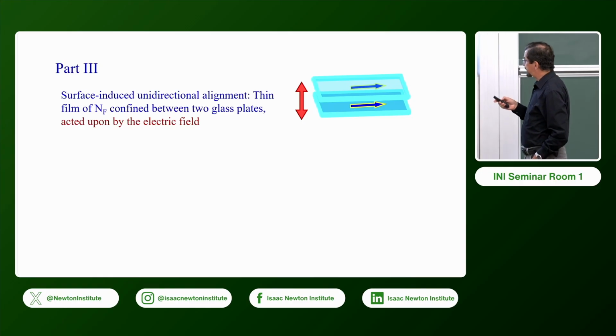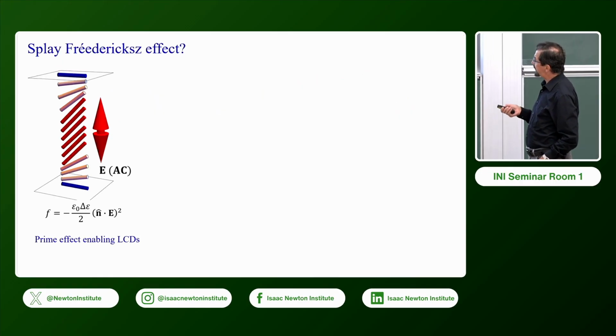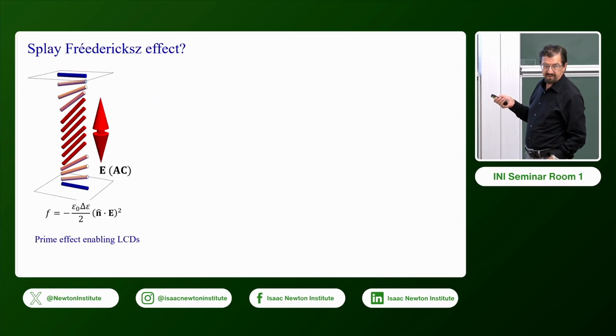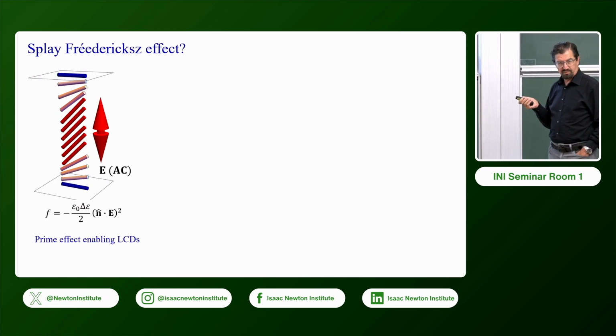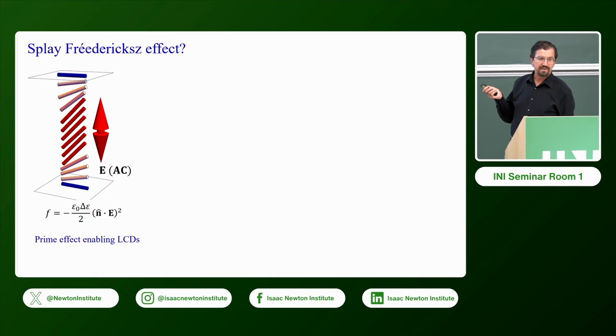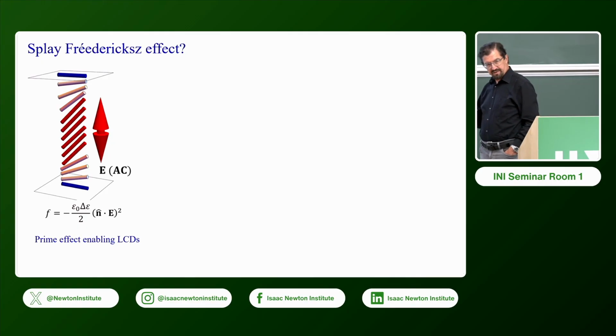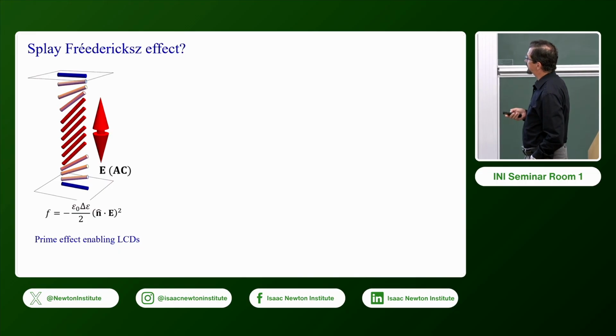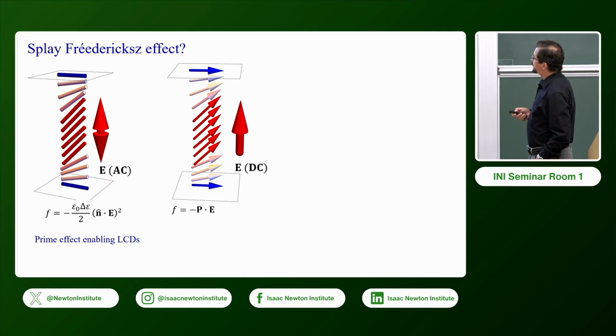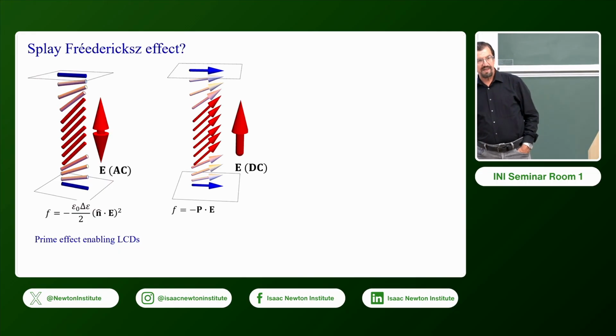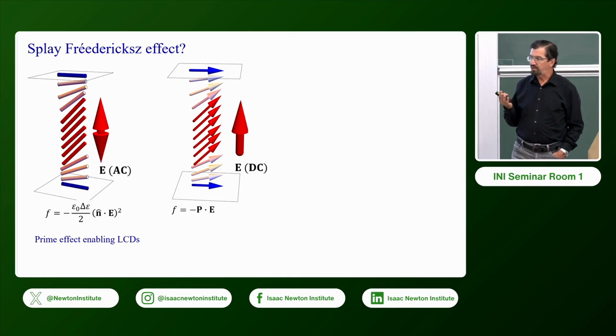And if the electric field is applied, then in the normal nematic, in paraelectric or nematic with quadrupolar symmetry, the director realigns along the field, and you have the change in effective birefringence of the material, and that or similar geometry is being used in display applications. Now, if the material is a ferroelectric nematic, then there is a polar order.